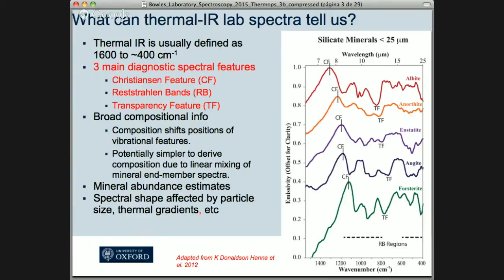The interesting thing is that because these are fine particulate spectra, they look quite different to the things that you'd get if you went into, say, the Arizona State University Thermal Emission Library, because they've got these interesting roll-offs and suppressions in Rastral band depths compared to the larger size fractions, for the reasons that were discussed yesterday in terms of volume scattering versus surface scattering. But the interesting thing is that they have broad compositional information. Composition shifts the positions of these features around. It's potentially simpler to derive composition because in theory, if everything's happening very close to the surface, you don't have much scattering going on, then you can imagine everything adding together linearly. So it makes unmixing the spectrum more straightforward if you've got spectra that look a bit like this, but have bigger size fractions, or you put the smaller size fractions in as a part of the unmixing process.